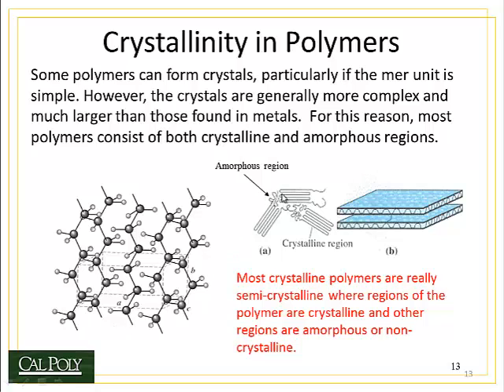And then there are regions of amorphous material between the crystals. These are called crystallites — they have the molecules lined up — with amorphous regions in between. When I say the material is semi-crystalline, I don't mean it's kind of crystalline. I mean that part of the material is crystalline and part of it is amorphous. Most crystalline polymers are actually semi-crystalline, and the amount of crystallinity can vary from as low as 5% up to a maximum of about 70%, with most polymers having percent crystallinities around 30%.